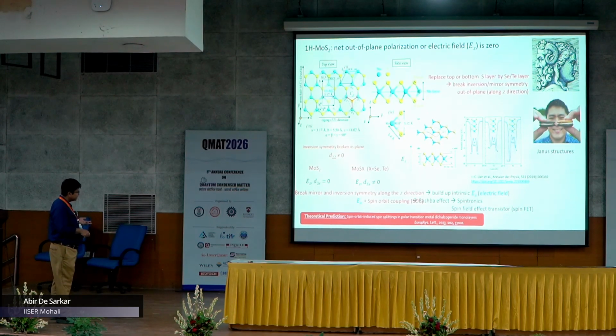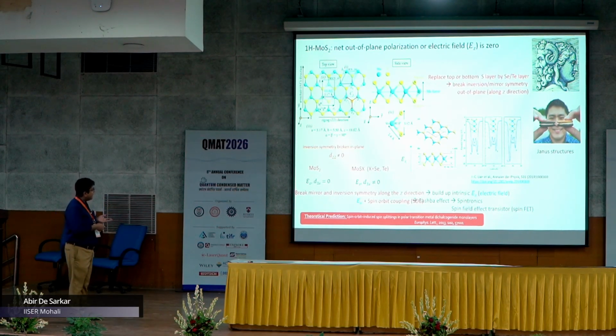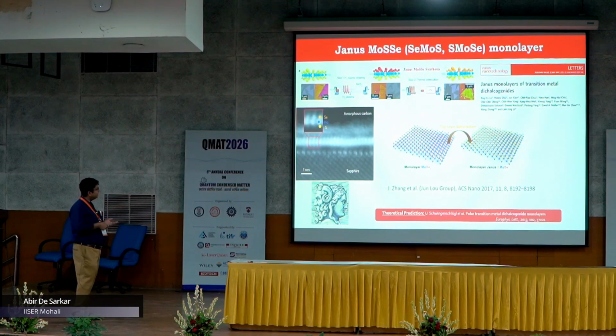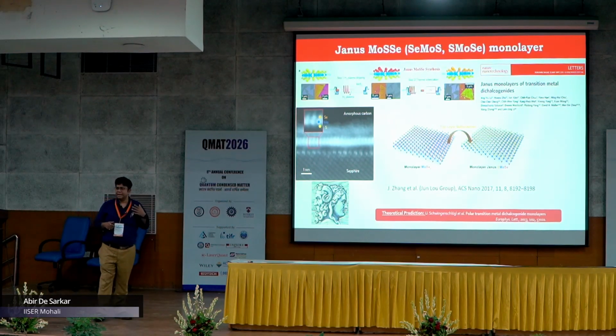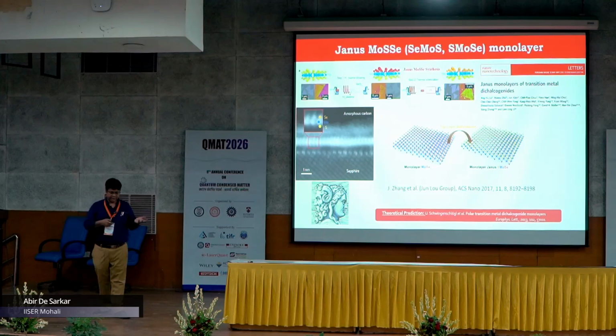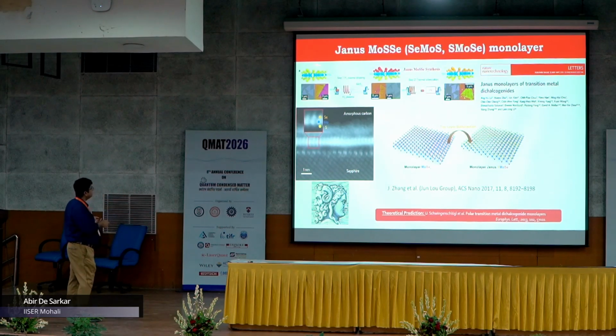The Janus structures were first reported theoretically in this EPL paper in the year 2013, and spin-orbit induced spin splittings in polar transition metal dichalcogenide monolayers was the motivation behind their work. And then a few years down the lane, the Janus structures have been synthesized experimentally, in two different experiments. Here they started off with a single layer of MoS2, and here the top layer has been selenized. And in another experiment, they began